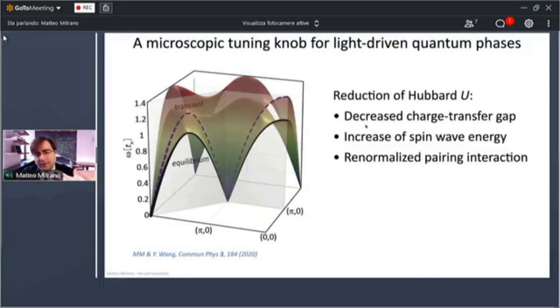With this, we are demonstrating that ultrafast lasers can be conceived as a microscopic tuning knob for light-driven quantum materials. A reduction of the Hubbard U in the cuprate is particularly impactful because in this material, this decreases the charge transfer gap. The charge transfer gap is anticorrelated with TC. So in principle, a lower charge transfer gap could increase the equilibrium TC and perhaps favor pairing out of equilibrium. Most importantly, if we are reducing the Hubbard U, we can actually affect also the spin wave energy and